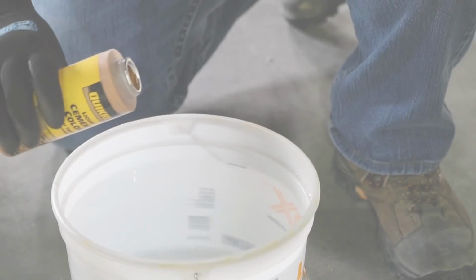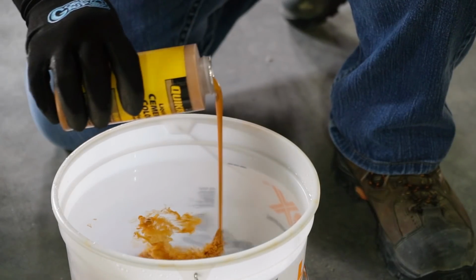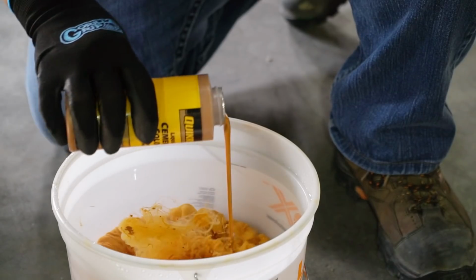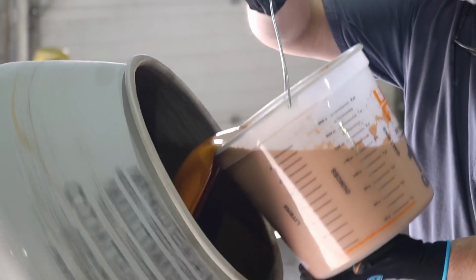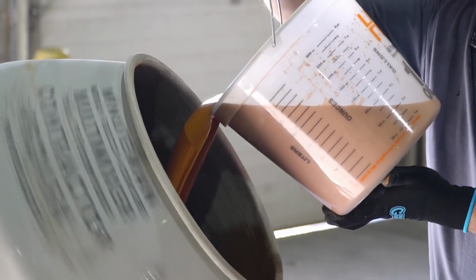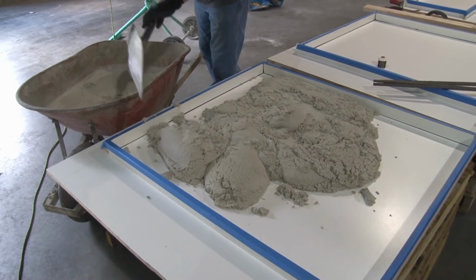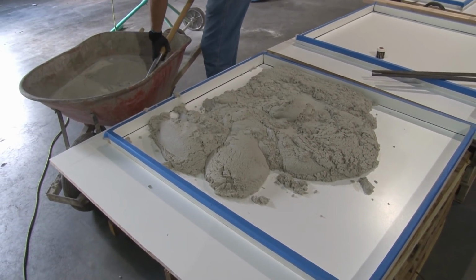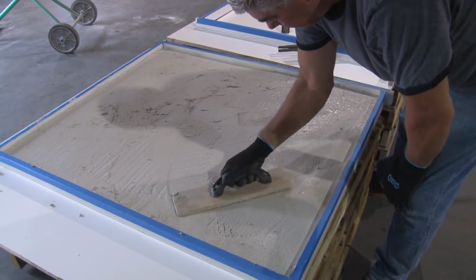The mix is formulated to perform equally well in a plastic or flowable consistency. To give the countertop an integral color, liquid cement color can be added to the mixing water before the water is added to the mixer. After mixing, fill the form, working continuously and making sure the mix is consolidated into the corners of the form.